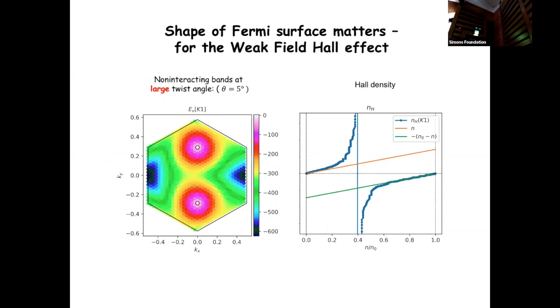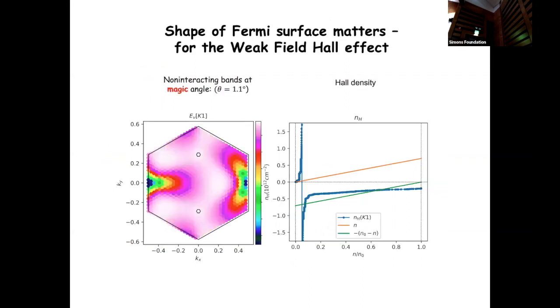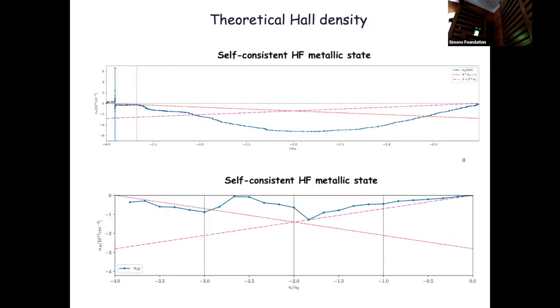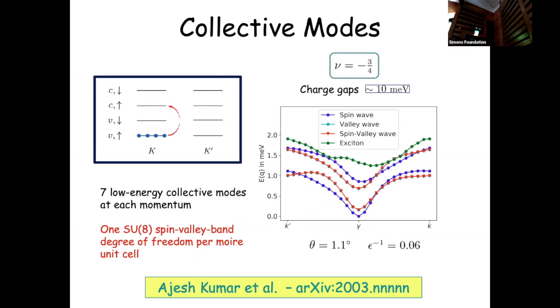If you compare that with an actual calculation for the non-interacting model of magic angle twisted bilayer graphene as a function of hole filling, the Hall density calculated using the correct formulas from Boltzmann transport theory doesn't match the hole density, and the jump from hole-like Hall density to electron-like Hall density occurs very far away from the middle of the band. Okay, 2 minutes. And we can sort of understand that. So, okay, I have 2 minutes left. I'm just going to try and get one idea across.